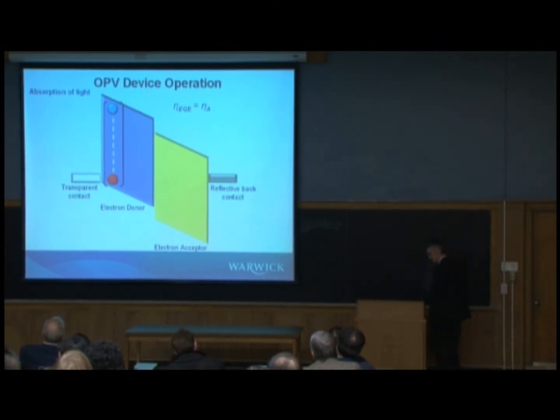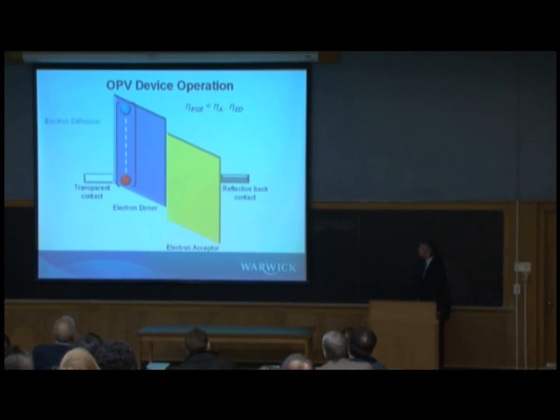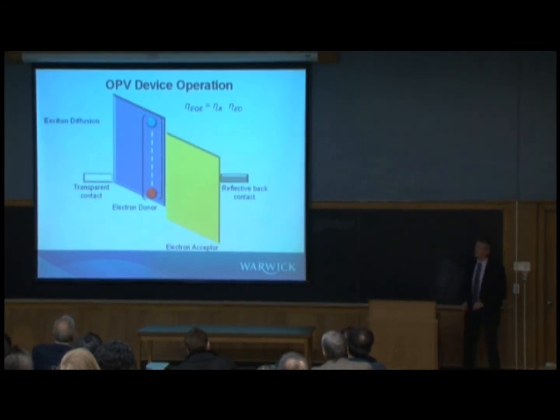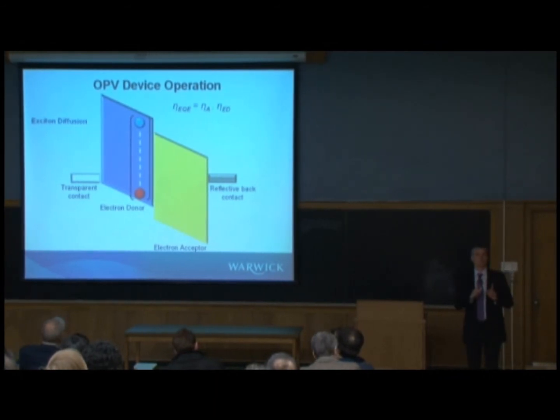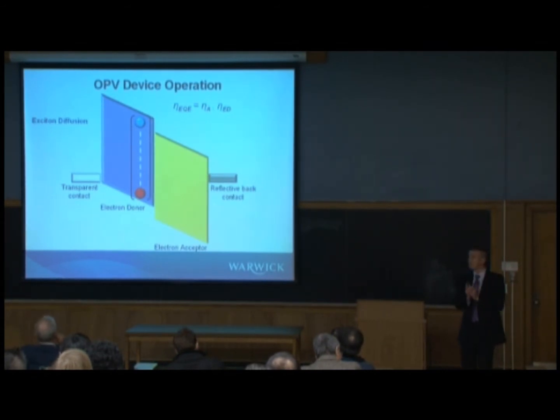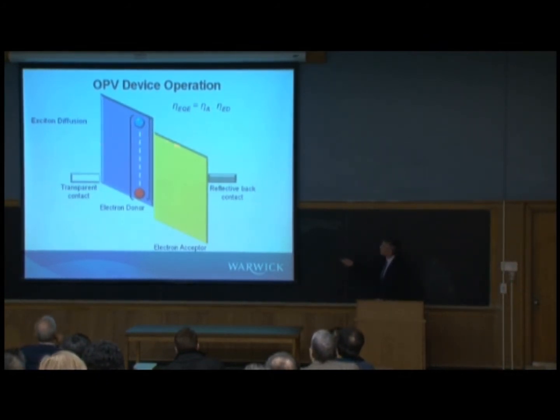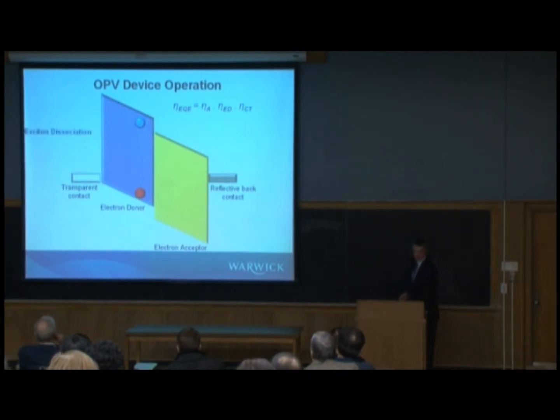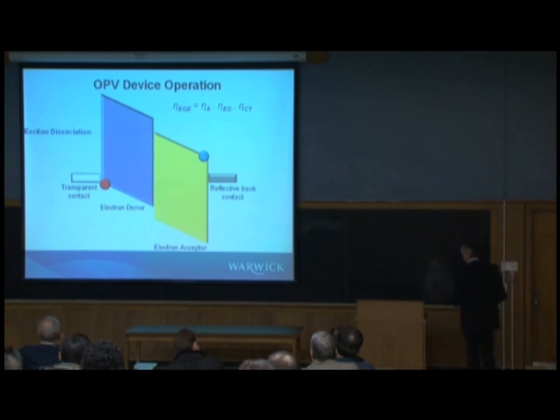So the next important step is diffusion of the exciton to that interface between the two different types of materials. And remember I said the diffusion length is low, a few tens of nanometers at most, so that places some constraints on the thickness of those layers. You can't have them too thick. Provided you then have an energy offset at that interface of sufficient magnitude to overcome the binding energy of the exciton, then the charges will separate, travel through the respective materials to the electrodes, and then they're collected.